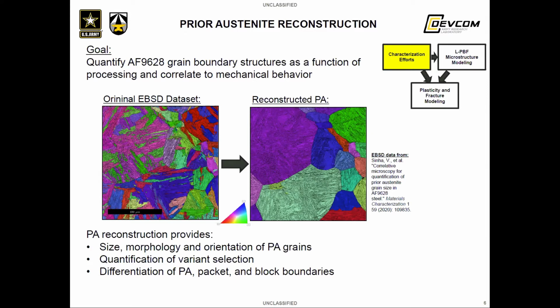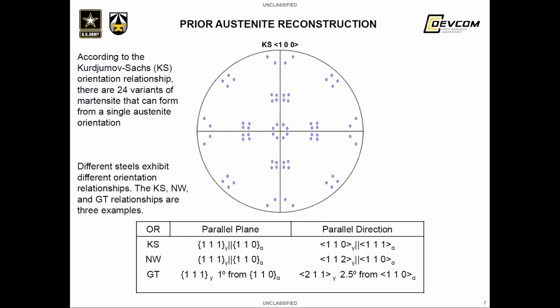Okay, in the following slide, the prior austenite reconstruction method relies on an orientation relationship between the parent austenite grains and the daughter martensite variants that form. Because the martensite transformation is non-diffusive, the transformation happens as a localized mechanical deformation. And it's that mechanical nature of this transformation that results in a specific set of martensite lath orientations that can be formed from a single austenite grain.